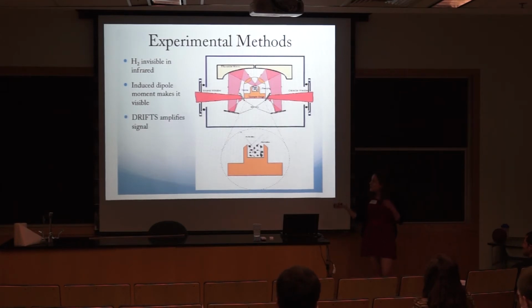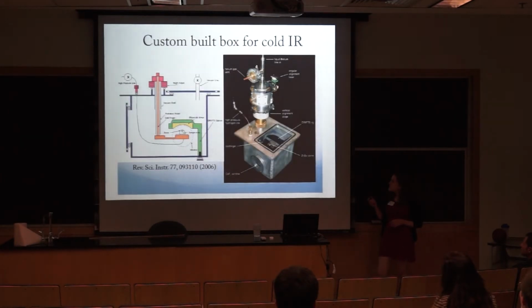So even though we've induced a dipole moment, the signal from the hydrogen is still pretty weak, so we have to use this technique called diffuse reflectance infrared spectroscopy, basically to amplify our signal. So that's a schematic of the mirrors and how that works to bounce the light around in the sample to get a higher signal. So this is our box or cryostat.